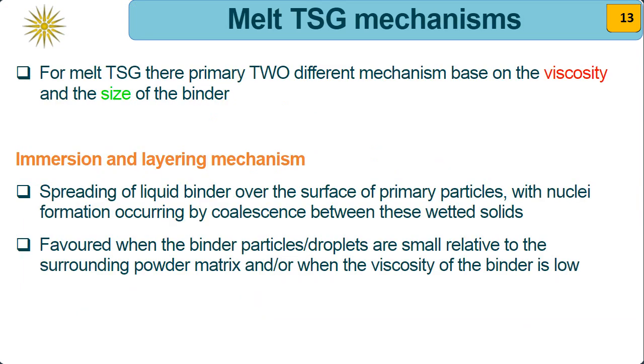The melt granulation mechanism has also been studied, and it was found that it primarily relates to two different mechanisms based on the viscosity and the size of the binder. The first mechanism is well known as the immersion and layering mechanism, and during this process we have the spreading of the liquid binder over the surface of primary particles, with the nuclei formation occurring by coalescence between those wetted solids. The favored mechanism takes place when the binder particles and droplets are small relative to the surrounding powder matrix or when the viscosity of the binder is low.